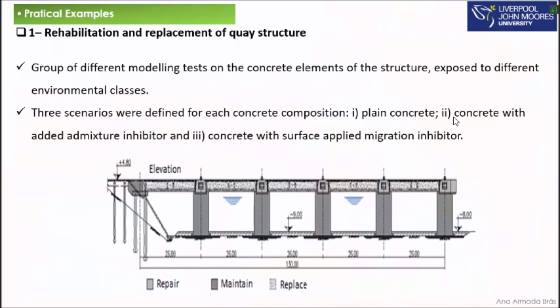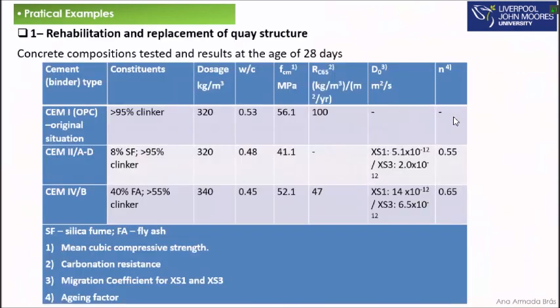For you, maybe sulfates also. And then three scenarios were defined for each concrete composition. So we tested plain concrete, concrete with admixed inhibitor, and concrete with surface applied migrating inhibitor. And then what we did, at the lab we got the physical and mechanical characteristics of three different types of concrete, as I mentioned before, and these are the results at 28 days.